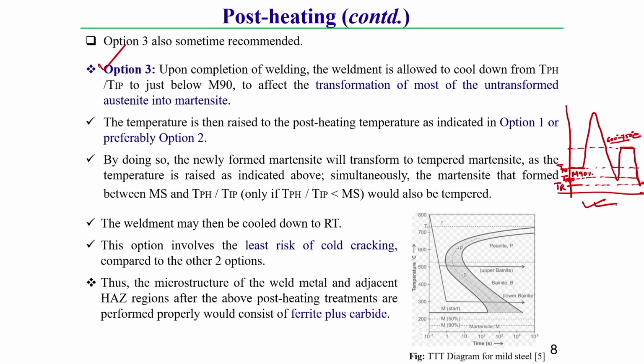By this option also we can drastically reduce the chances of hydrogen induced cracking. Keep this in mind. This type of heat treatment is also preferable in the case of ferritic steel. Due to this heat treatment process, there is a chance of formation of martensite down to preheating temperature, and whatever untransformed austenite was there, on cooling below the martensitic 90% transformation temperature range, that untransformed austenite will be converted to martensite.